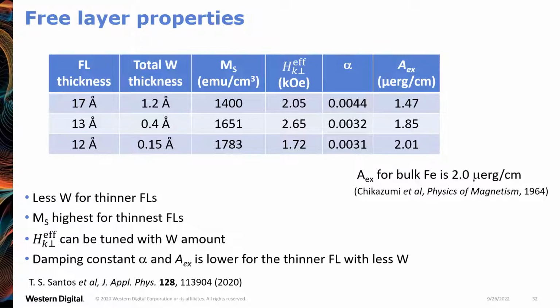Yes. The other question I have is, the boron diffusion is already known to the community. Was the choice of cobalt iron boron deliberate, to leave out the boron and make a better crystalline structure of CoFe? If not, then why not directly use cobalt iron and not cobalt iron boron? Okay. The boron is necessary to do this trick of a solid phase epitaxy using a sputtering process, a manufacturable process. So this is why we deal with the boron.